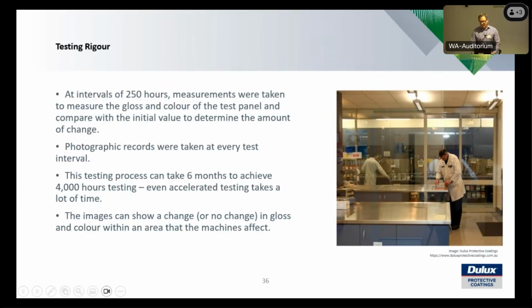So the testing rigour for both tests, intervals of 250 hours, and from that they were able to take measurements of gloss and colour of the test panel and compare those with initial value of what the starting point was. Photographic records were taken. Although the testing process was long, 6 months, it still far outweighed, sometimes the 10, 20 years where companies like ourselves have got panels out there in the field within their laboratory sort of departments and evaluating them every 6, 12 months.